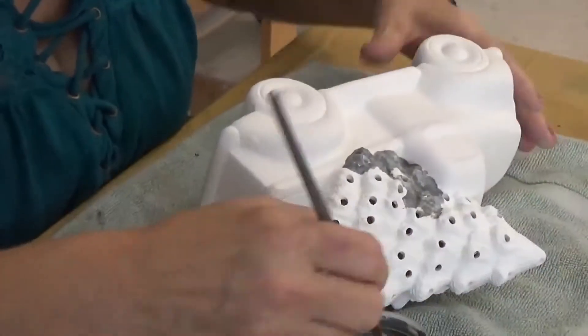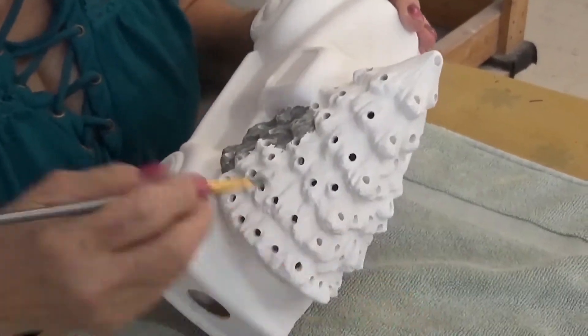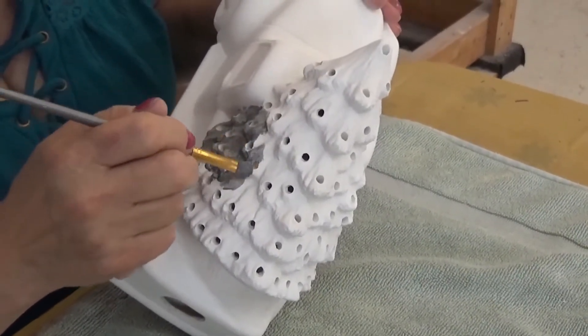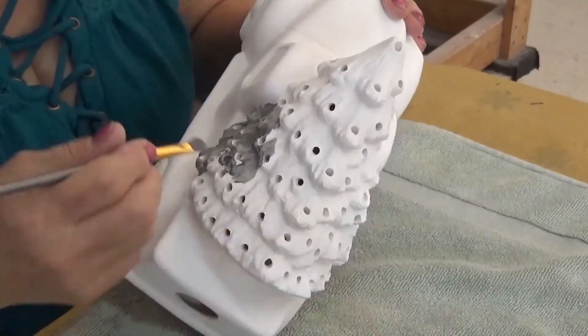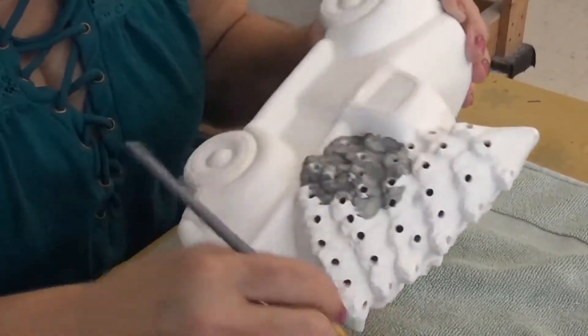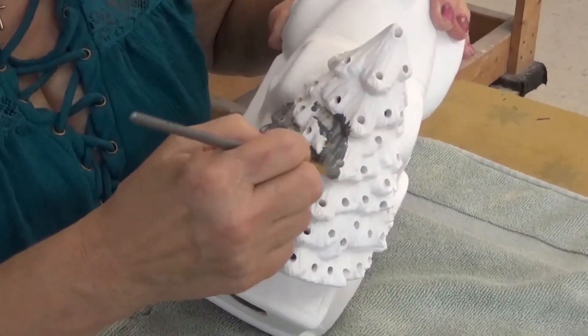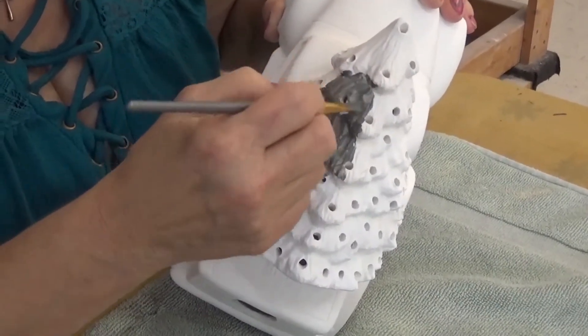This lid is making me nuts, so I'm going to switch over to the jar — I'm not able to get enough paint. I'm a heavy-handed painter, which is okay as long as you keep things nice and neat. I'm not pressing really hard; I'm pressing very lightly. Because if you press real hard, you think you're doing a good job putting the paint on, but what you're really doing is pulling it away from the bisque — instead of putting it on, you're actually taking it off. So you want to make sure you stay nice and smooth. You can't tell by looking at it now, but when I put it in the kiln there are no secrets anymore — it all shows up. And I'm going to go all the way around this entire tray. You don't have to go the same direction like you do on the other one, because when you fire this, it all just lays flat real nice. If you do it exactly like I say, yours will come out just as beautiful as mine.